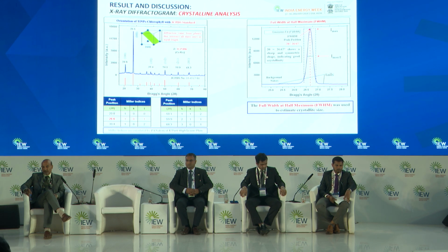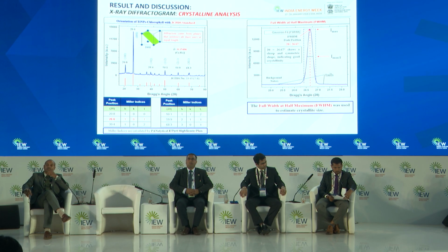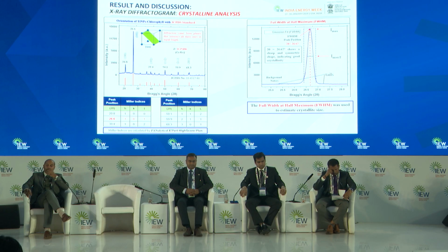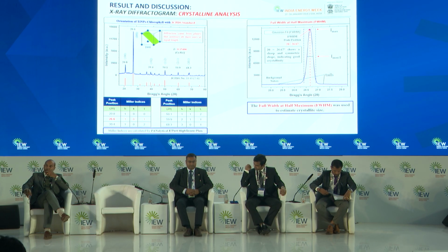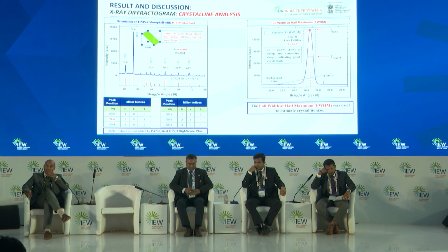Again, we went for X-ray diffraction. This was to analyze the crystalline structure. You can see those XRD peaks confirm the anatase phase of TiO2. The anatase phase of TiO2 confirms the charge transfer, charge generation actually in this hybrid material, right?